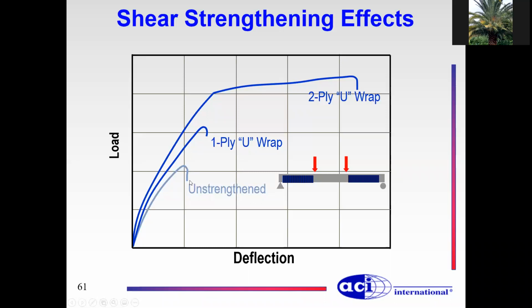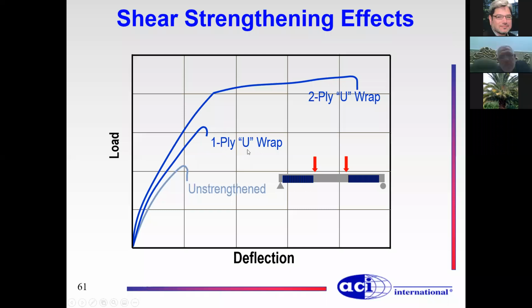So if you have a typical shear critical beam, unstrengthened, it will fail like that. As you know, shear failure is usually brittle, unlike flexural failure. So you don't see any plateau, you don't see any ductility in the behavior. If I use one ply or one layer of reinforcement for FRP, I might get an increase in the capacity in shear, but again, it's going to fail in shear, and it's also brittle.